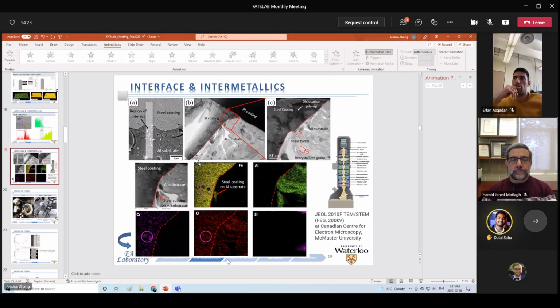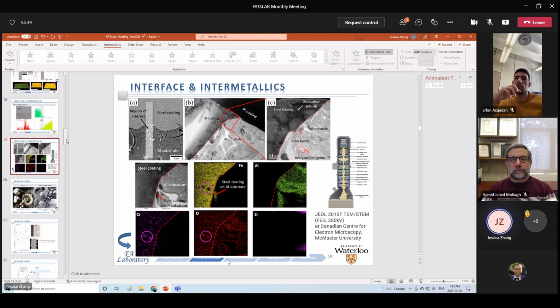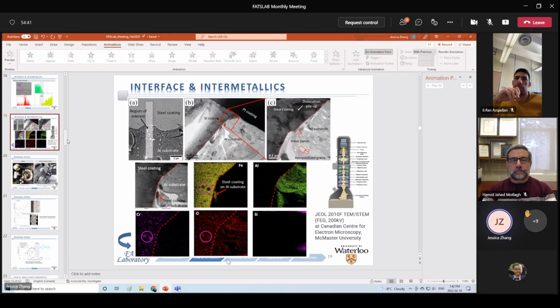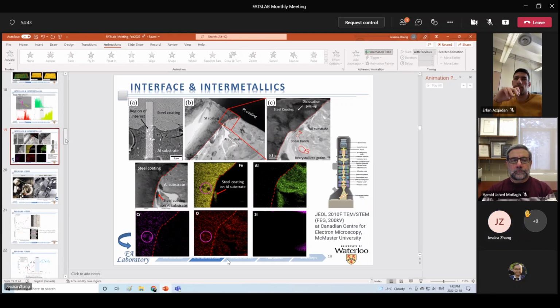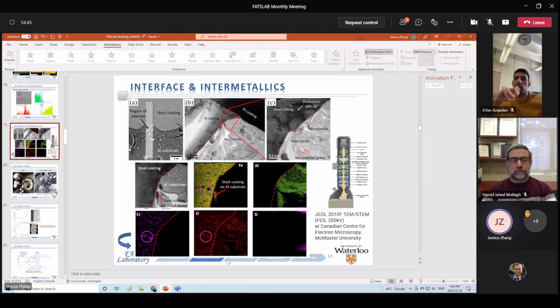Yeah, and I would also add that during our adhesion study, since we were able to view our samples from the fracture surface, we can also see the surface of the coating. And we found a kind of strange webbed texture, and Dalal did a little bit of a study on that to see if it has the potential to be an intermetallic. However, we're not so confident about that, so we cannot claim it as of yet.